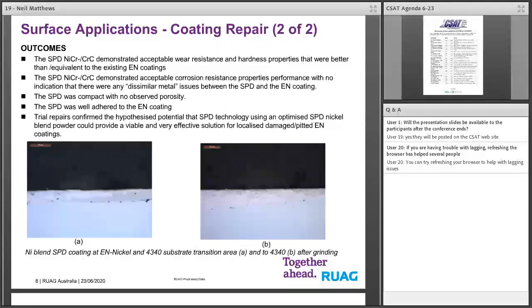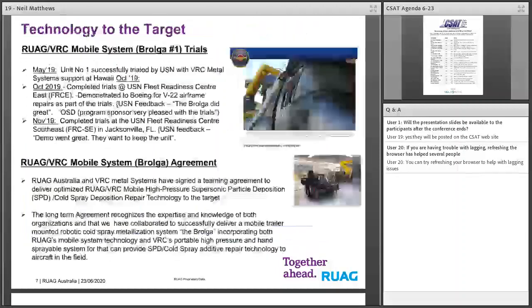And if you look at the micro sections there, you can see basically how the deposition is adhering to the microstructure, or to the substrate and the chrome. We've effectively released that now as an approved repair, and that will certainly assist us in turning product back into service very quickly. The next slide, thanks.